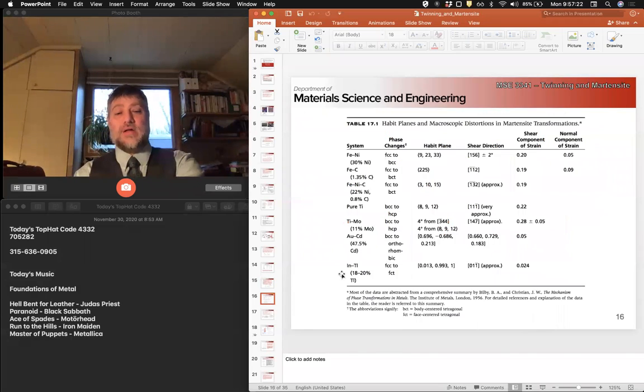Okay. So if we look here at different systems, we can see that the shear component of the transformation is quite large. Okay, so if we look at iron, carbon, steel, right? Remember FCC to BCT, right? This is the habit plane and the shear direction, but take a look at the amount of shear strain associated with martensite formation. 20% strain, right? 20% shear strain. That's huge, right? What is the elastic limit, right? How much shear strain do we accommodate elastically, right? What's the offset that you use when doing a stress strain analysis?